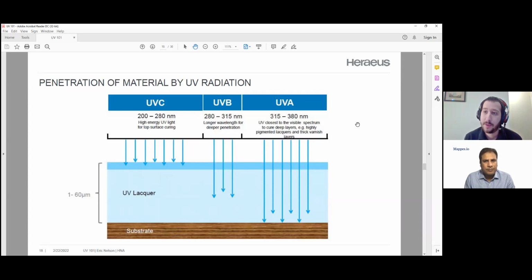But on the other hand, this means that you're going to get very high curing and very high properties on the outer surface. So one of the things that we see with UV LED, which produces only UVA energy, is that it's very good at bonding. It's very good at penetrating deep into materials. It's not very good for getting good surface properties. So if you need to have a very dry surface, a very hard surface, a tack-free outer surface, you're probably going to want to use a broadband UV output and not a UV LED. Got it.